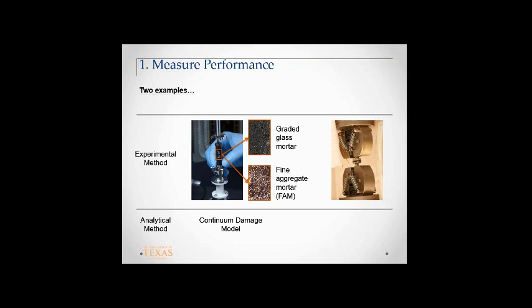I'm collaborating with a professor in physics, Professor Michael Downer. His name is not here, but I think I should mention it. He specializes in optics, so he's able to look at real-time changes in these microstructures as a function of temperature. So we look at these structures appear and disappear as you change the temperature on the specimen. And then what we've done is we've taken this same thermal history that he's applied and applied it to the asphalt binder in a rheometer.